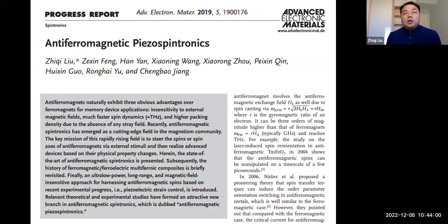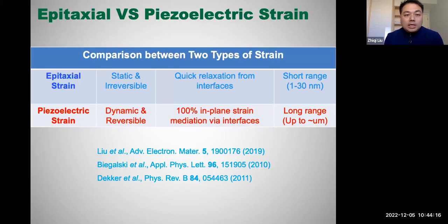We also proposed this idea, so-called antiferromagnetic piezo spintronics, to try to use piezoelectric strain to control antiferromagnetic spins. The last point I want to bring to the audience is an interesting comparison between two types of strain. One is epitaxial strain. For example, if we do epitaxial growth for oxides, we will have static and irreversible strain that will quickly relax from the interfaces.